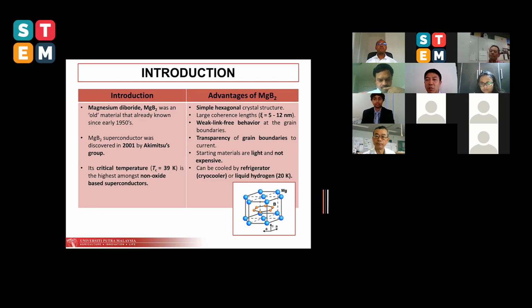There are a few advantages of why we choose MgB2 as the material to enhance the critical current density. The crystal structure is very simple. It's a binary compound. The coherence length is larger if you compare to copper oxide-based superconductors. Also, this material has weak-link-free behavior at the grain boundary. Again, if you compare to high Tc superconductors, this is definitely one of the great advantages. Starting materials are light, especially boron. And magnesium is actually not a very expensive material. Because of the slightly higher Tc of about 39 Kelvin, we can make use of a refrigerator or cryocooler, or even liquid hydrogen with a boiling point of about 20 Kelvin, to cool this material.